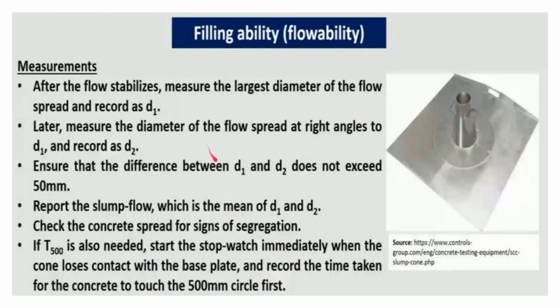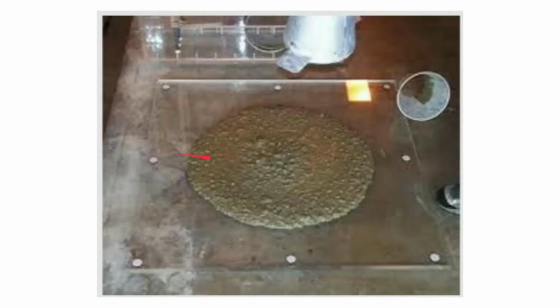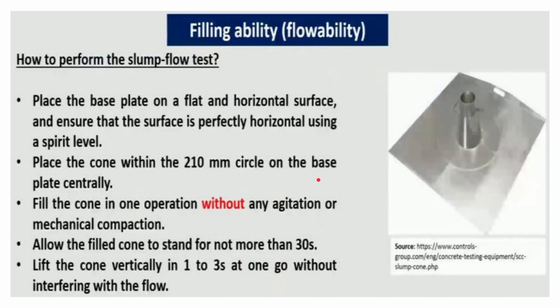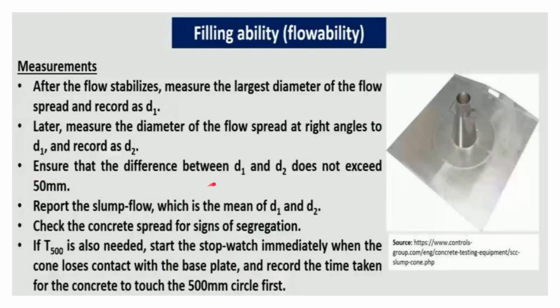Then we measure the diameter of the flow spread at right angle to D1. Say for example if we have measured this way, now we will measure at 90 degrees, so this way it will be the D2 diameter. Thirdly, we check that the difference between D1 and D2 does not exceed 50 mm. This is one of the parameters we have to check, so it should not be exceeding 50 mm.